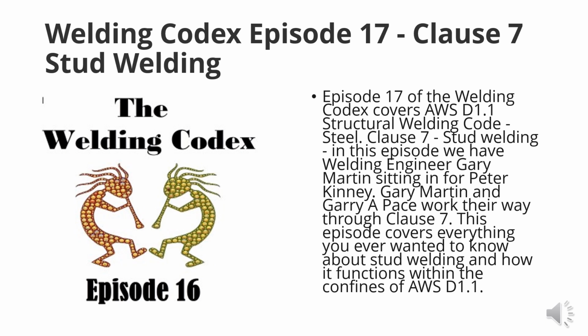There were a lot of changes in the 2020 verbiage, starting back to what would be 7.6.1 or 9.6.1 in the 2020. It listed out that separated pre-qualified WPSs: studs conforming to 9.2.6, which are shop or field applied in the flat position to a planar and horizontal surface to steel base metals in groups 1 or 2 per table 5.3 are deemed qualified by virtue of the manufacturer's stud base qualification when welding is performed within the ranges of amperage and time of the manufacturer's welding recommendations. The limit of flat position is defined as 0 to 15 slope on the surface to which the stud is applied.